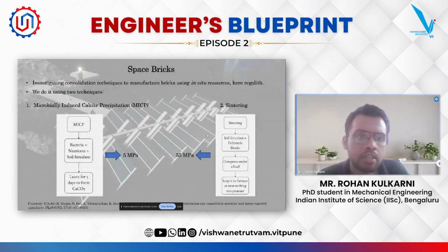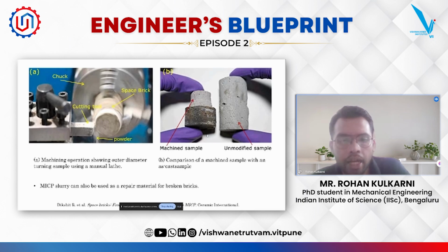In this MICP method that we use, we use bacteria. So if you apply the slurry that we have formed with the MICP method on the broken bricks, your bricks will be repaired. We have recently published a paper where we have extensively explained this repairing method, where you can actually control the damage that has been caused due to micrometeorites on your space bricks.